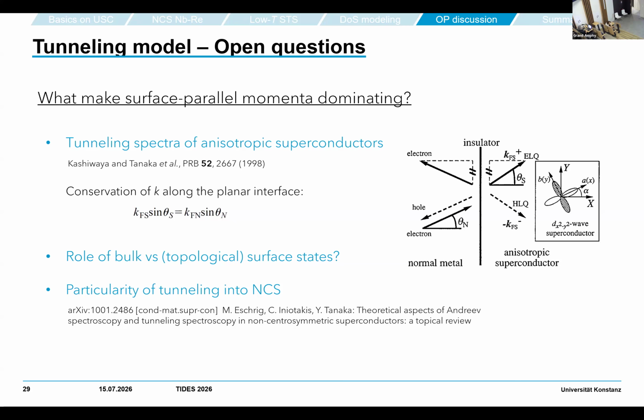I'll ask one short extra question: is there any degree of freedom in changing the tip that could actually change this selection, using iridium? Yeah, it's platinum iridium, and we tested with different tips, but they were all platinum iridium. Probably we should try another metal, tungsten or so - this is a good point, we haven't done this. Usually we do this with platinum iridium.